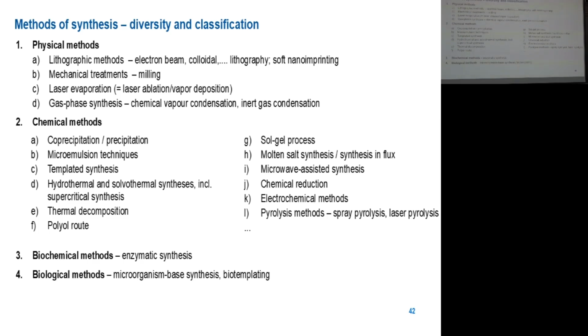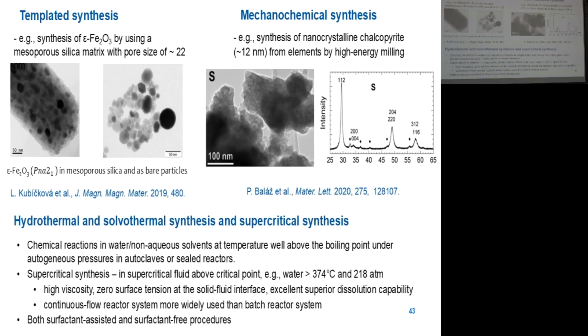And maybe a modified version of the coprecipitation procedure can be found even in some templated synthesis, where we can, for example, do the coprecipitation in some mesoporous matrix. You can prepare, for example, mesoporous silica with certain cavities, like cavities with a diameter of 22 nanometers, using some special polymer as precursor, and then you can impregnate this mesoporous material with iron nitrate, and you can do even precipitation inside the cavities and later apply some thermal treatment.